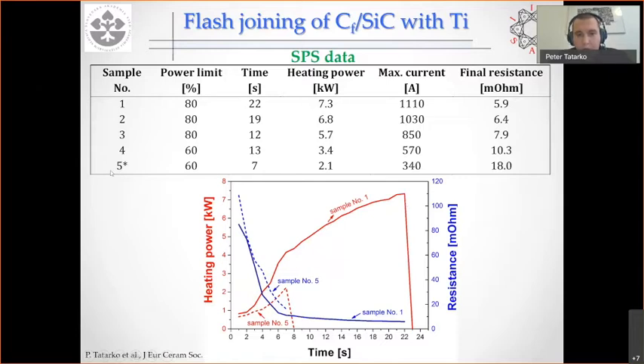But on the other hand, for the last sample, we dropped it here and it just fell down. So our idea, or our results, showed that it works. You just need to stop or interrupt the process at the right time. So if you interrupt your process once the resistance drops and reaches the plateau, then it's just the right time to interrupt the process. So it was all fine.